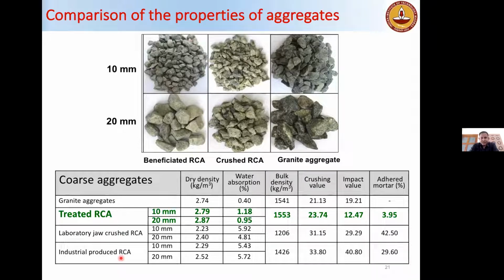As far as the physical properties are concerned, we all know that water absorption is a good indication when you try to compare the different kinds of recycled aggregates. You can see that we were able to bring the water absorption close to 1%, and usually it could be 5 to 6%. And the mechanical properties are also as good as the granite aggregates. The next slide, let me show you the fine aggregates.